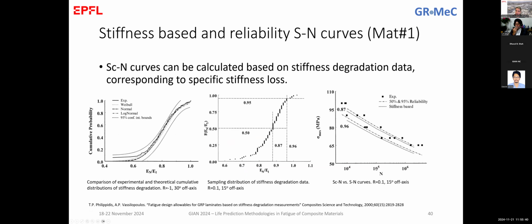So what we see in this diagram, we have the experimental data. This is again the material number one, the first one that we extensively discussed yesterday. And this is the material at 15 degrees off-axis, R equal to 0.1. The 50% reliability SN curves and 95% reliability SN curves for the material are plotted with this dashed dot line. So this line and this line. And here you see the stiffness-based SN curves for 87% stiffness degradation or 96%. Sorry, 87% remaining stiffness. So this is 13% stiffness degradation, or only 96% remaining stiffness, which means only 4% stiffness degradation.